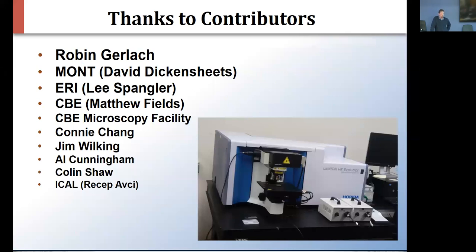It is very much complementary to FTIR, and as a matter of fact, we're waiting to have an FTIR microscope and an ATR-FTIR installed, not in my lab. There are one or two on campus that are a little older, but this should help us get, again, more insight. And just like Raman, FTIR is non-destructive, so you can get a Raman spectrum, get an FTIR spectrum, and then go on to XRD, XPS, Auger spectroscopy, whatever you decide to do. These are great techniques to get started on a sample because you're not destroying it, unless you shine a laser on it for too long. You do see decolorization when you have your laser on for too long, on some samples anyway.